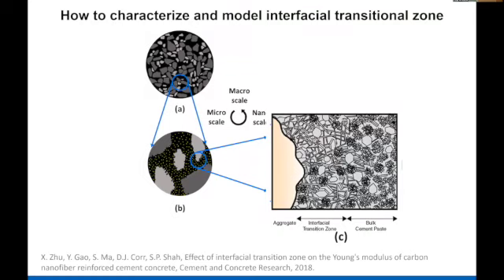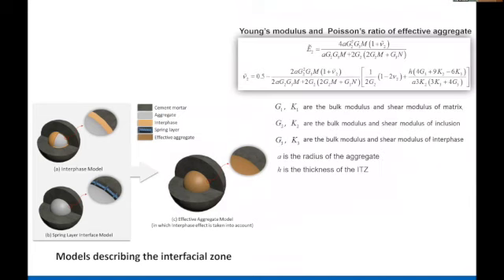The interface between aggregate and cement is rather porous, and we suspected that addition of nanofiber alters that interface. To check that out, we did some combined analytical and experimental work. So first we look at the solution of a three-phase material: spherical aggregate surrounded by an annulus of interface in an infinite matrix. You have an analytic solution if you know the modulus of the three phases, aggregate, interface, and the matrix.